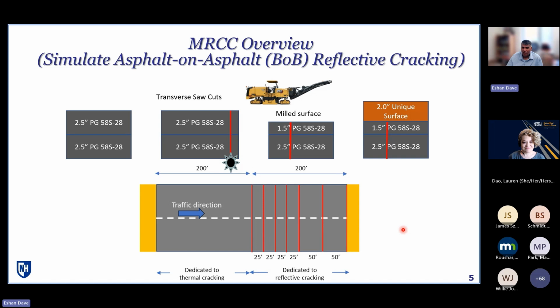Any benefit you can get from any sealing action that's still left behind in the underlying pavement, together with any load transfer that you can get, I would take it. That said, I would definitely be suspicious if there's a lot of water coming through those underlying cracks, or if the cracks have really tented and there's a lot of loose material. I would recommend milling it until you get to a more sound layer prior to overlaying. So that would be my recommendation to prevent that damage from incompressible particles or moisture.